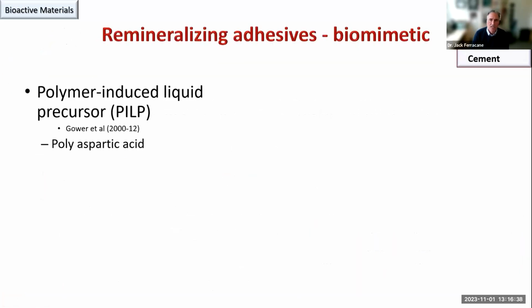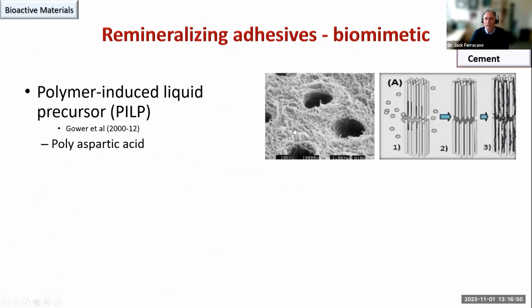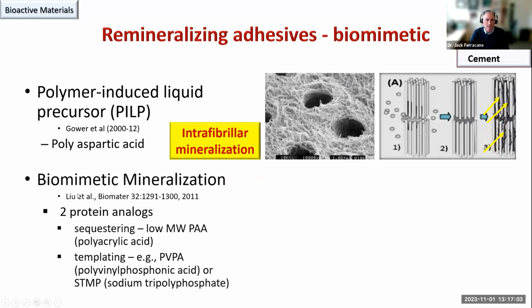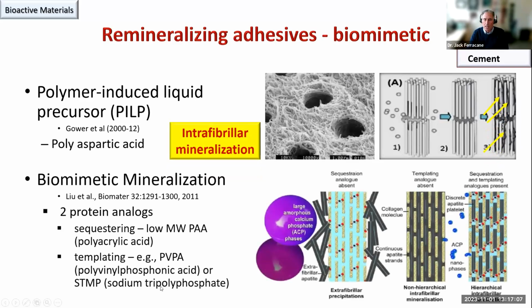Now, the last thing to mention is this concept of biomimetics. Polymer-induced liquid precursors. This is work from Laurie Gower when she was back at UCSF, now in Florida, putting polyaspartic acid soaking into a demineralized dentin surface. And this allows for calcium to enter and get sequestered and actually form mineral in an intrafibrillar pattern. Similar work from Franklin Tay's group using different protein analogs and a templating molecule. What he shows here is that here's the demineralized collagen. And if we don't get the imprinting molecules and the templating molecules in here, we'll form calcium phosphate on the surface. And that's not really a biomimetic material. But if we allow the material to soak in with the polyacrylic acid and the PVPA, we can now get calcium and phosphate sequestered intrafibrillarly and get mineralization to form there.